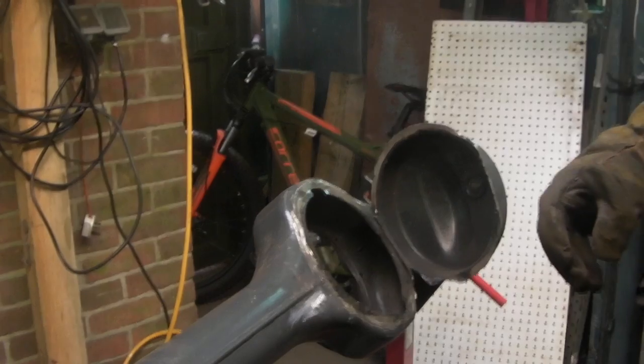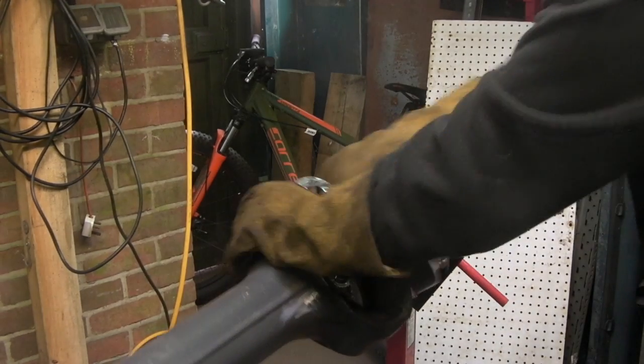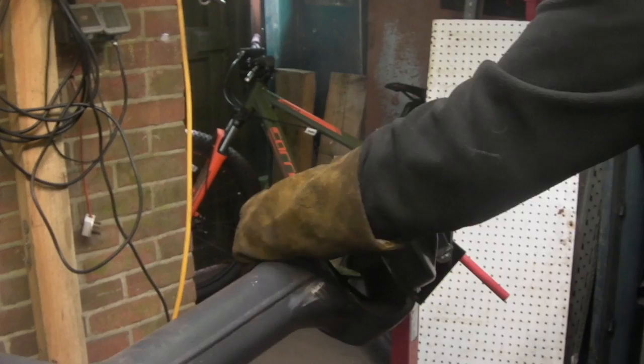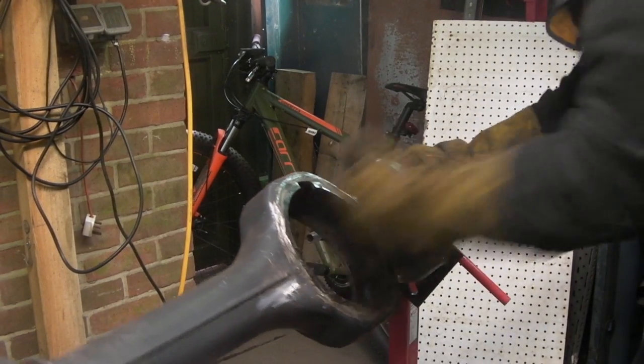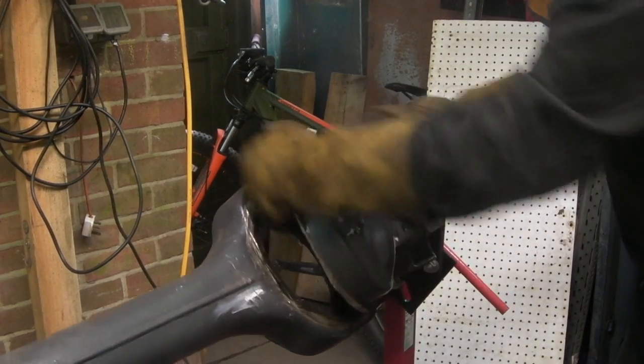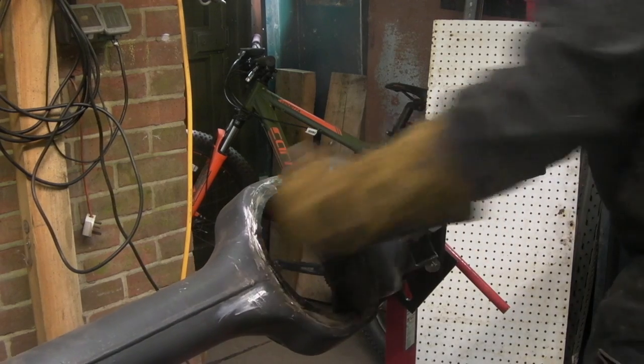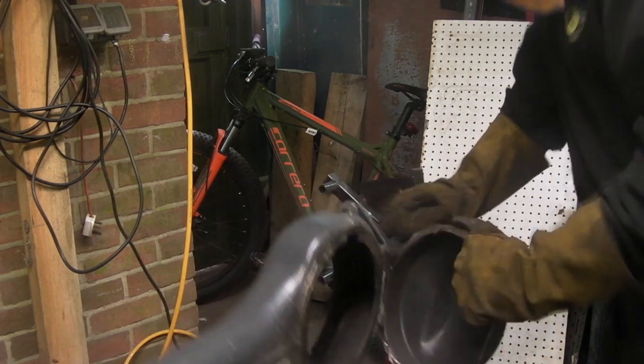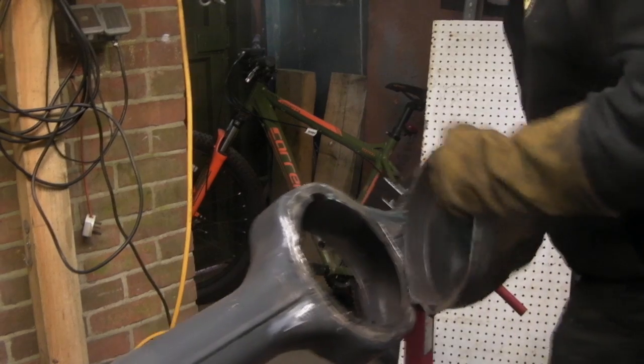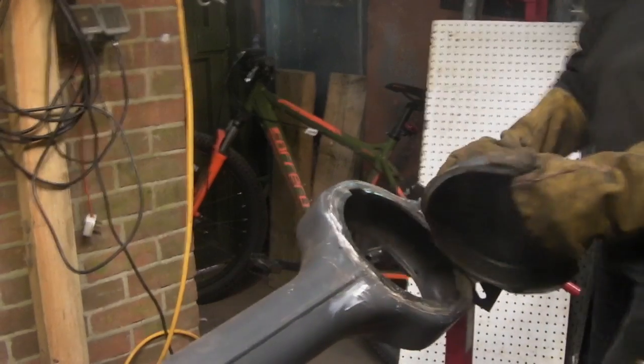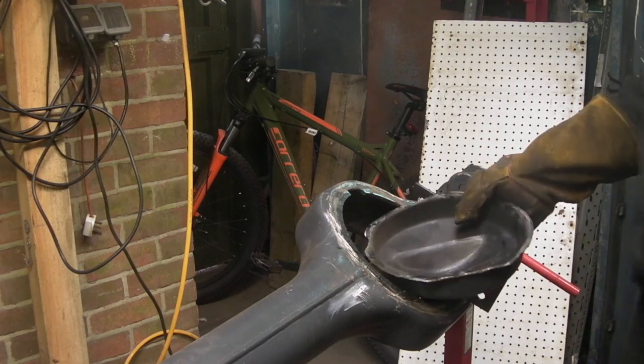Okay, just switch the grinder off, put it down, and then just fatigue the metal until it breaks. The pan is only about 1.5 mm thick, and basically it is quite weak. It's weaker than iron, as you can see here. So there you go, a bit of chimpanzee force, and it's off.